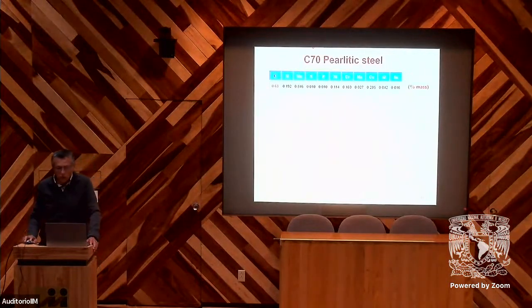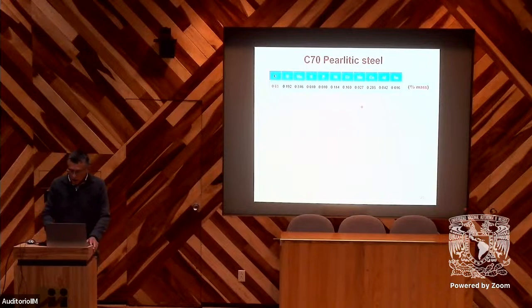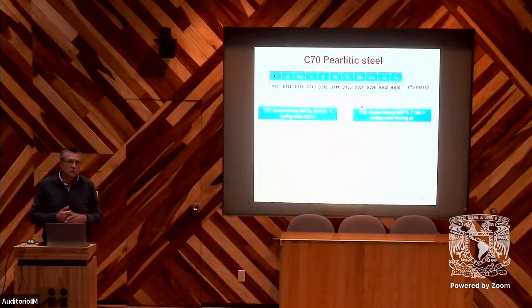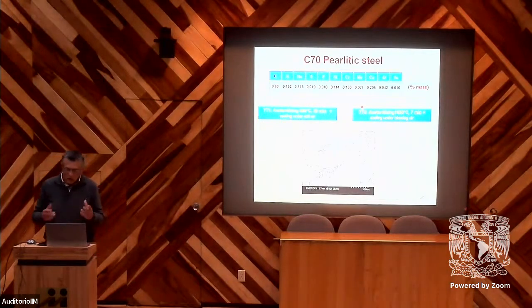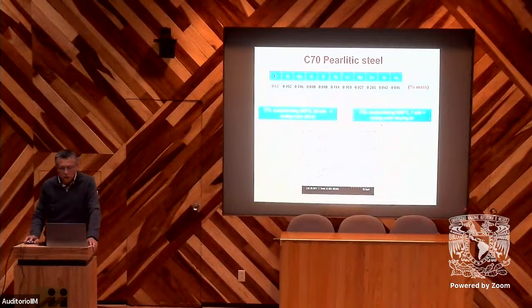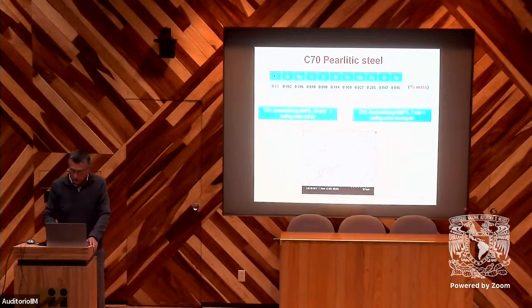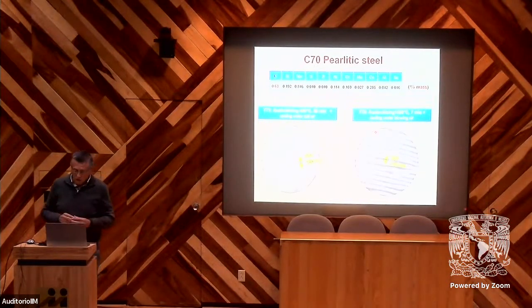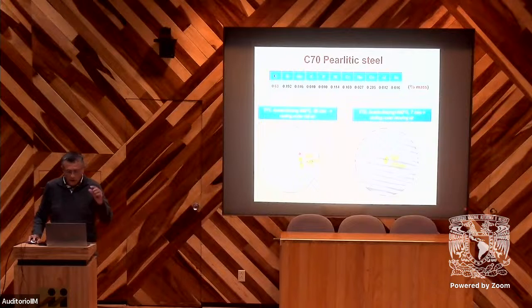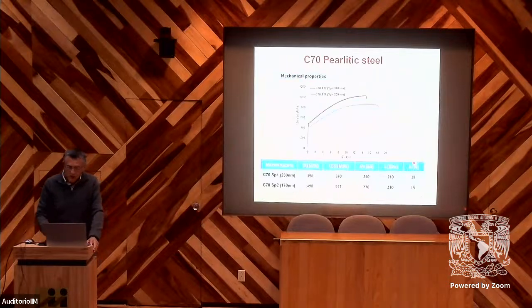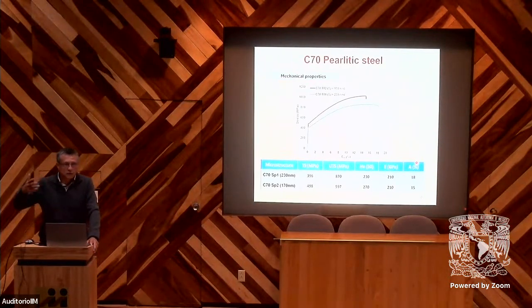For this study, we used steel containing about 0.7% carbon, and we tried many heat treatment conditions, and we can compare only two conditions of treatment. For this treatment, we always have 100% pearlite, but we have little differences. The difference here is the interlamellar spacing. We can observe here the difference between the two treatments, and this gives very important differences in fatigue behavior.